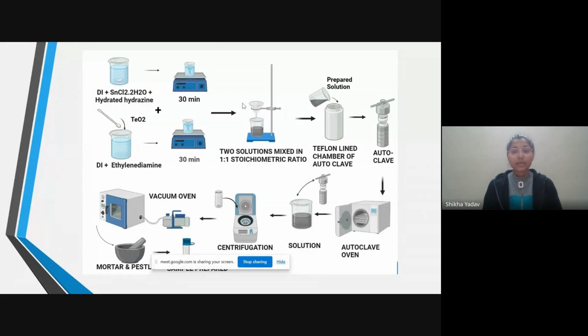After mixing these two mixtures, we transferred our solution to the Teflon-lined chamber. We know that the Teflon-lined chamber is able to withstand high temperature and high pressure. Therefore, we poured our solution into this Teflon, and then finally we packed it in an autoclave. Since we are following the hydrothermal method, the reason for choosing this method is that it is cost effective, easy to perform, and takes less time as compared to other methods. After packing the solution in the autoclave, we kept it in the oven at 150 degrees Celsius for 24 hours.